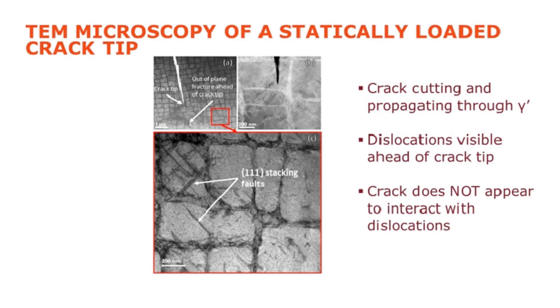We would expect to see slip occurring on those planes, but interestingly, the crack doesn't really appear to interact with them. So I think if this mechanism was fatigue driven or if plasticity was particularly important, we perhaps would see the crack interacting and propagating a little bit more on those planes than we do. But we don't. It seems to just carry straight on ahead on the cube planes.